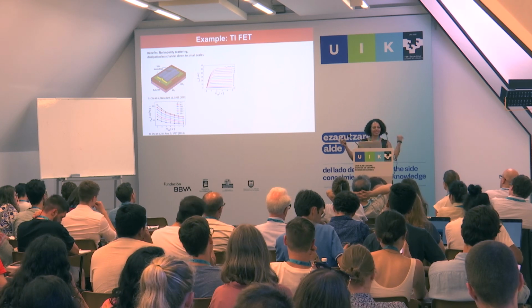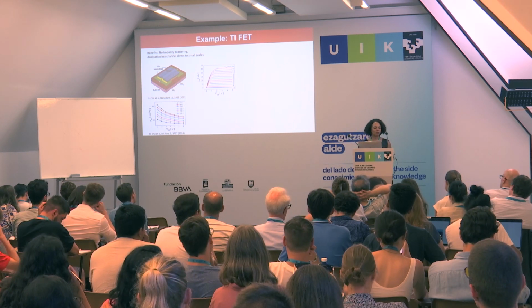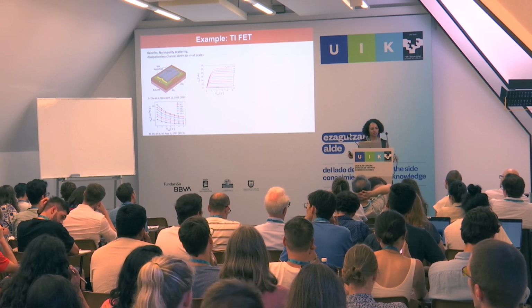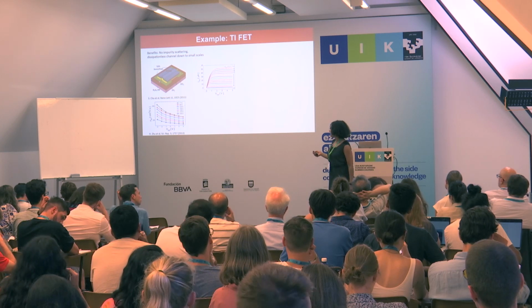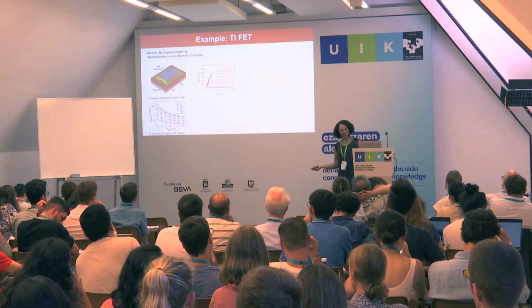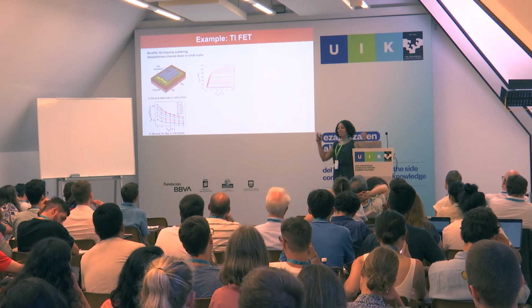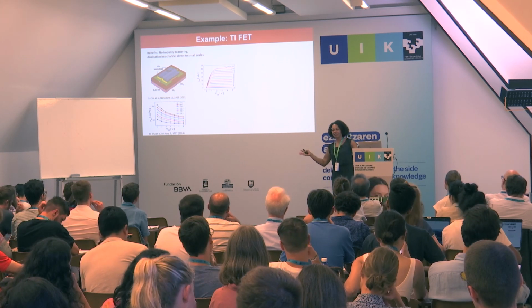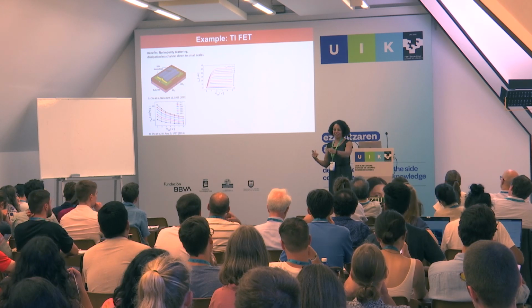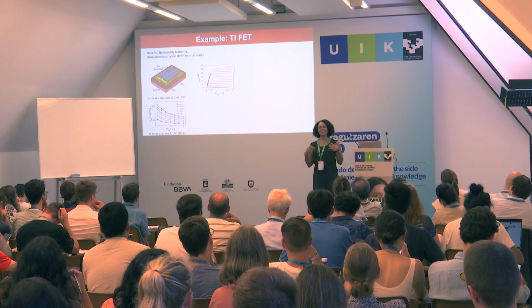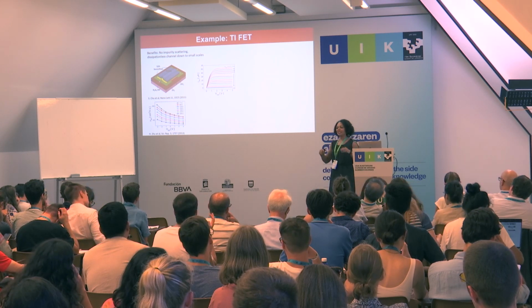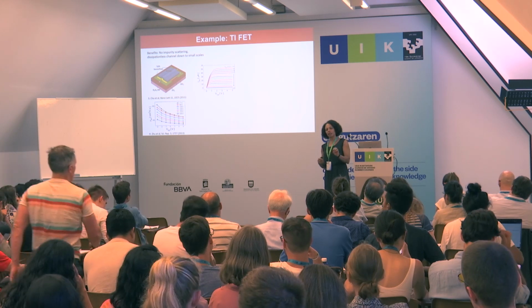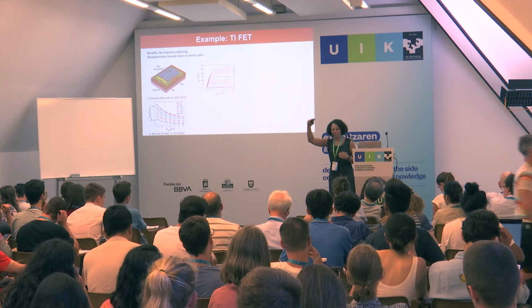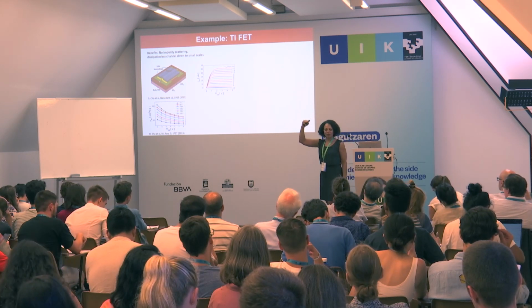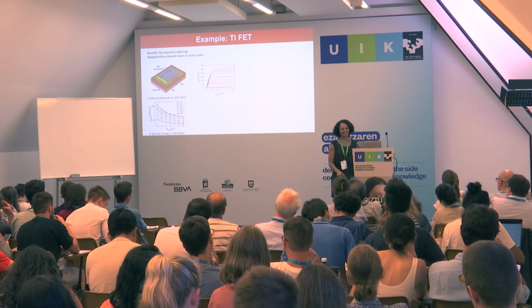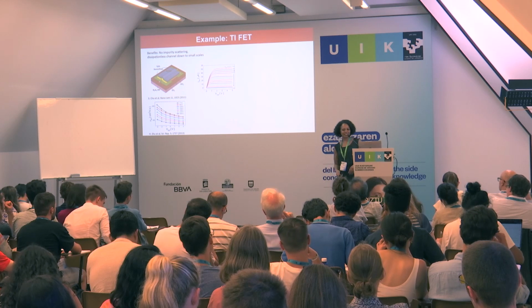there's enough of a surface that scattering can happen along the length, and this could be 100 nanometers, right? By 1D, I don't think it's 5 nanometers, it's like 100 or 200. And what Fawn was saying is exactly the point, that we have to be careful. This is partly why I wanted to talk about these things, because when we talk about things like lack of backscattering, my mind immediately jumps to, okay, it's dissipationless, but that's not really true, right? Every other scattering happens, just not directly backwards, but you can get side scattering, so you're still limited by that in these systems. The scattering is still better than you get in a semiconductor, but then you don't have enough carriers to actually take advantage of that benefit. That's a problem. So it's neither truly ballistic, nor are you high current in these cases, so you're just killed in that in-between regime, unfortunately.